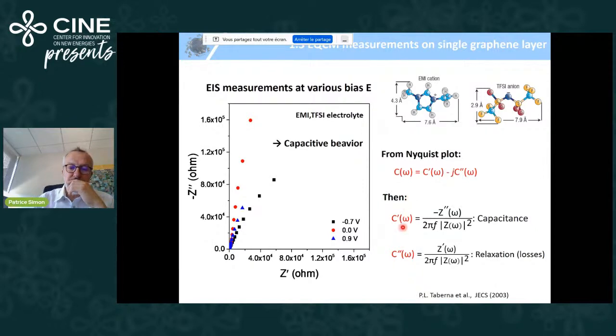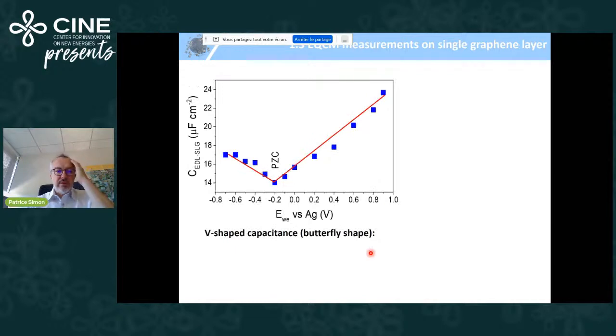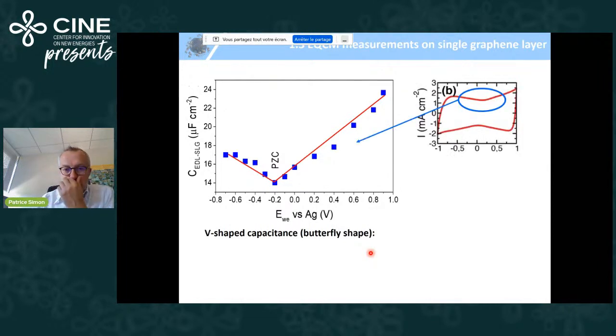that we developed years ago to calculate the real part of the capacitance, which can be obtained from the impedance data. It's basically the slope at low frequency, but not only. And then you can plot the change of the double layer capacitance, I would say the interfacial capacitance, versus the potential. What you see is that we have a V-shaped capacitance change, a butterfly shape. And this butterfly shape in the literature was explained by several different theories.